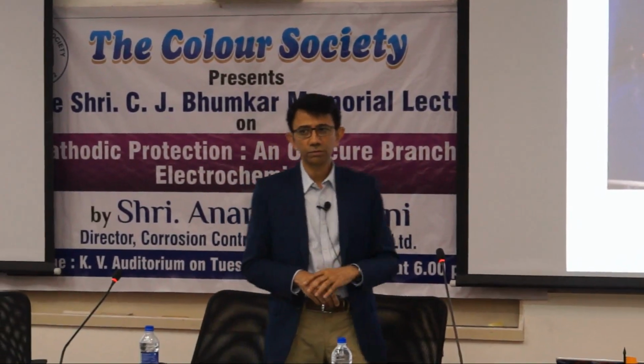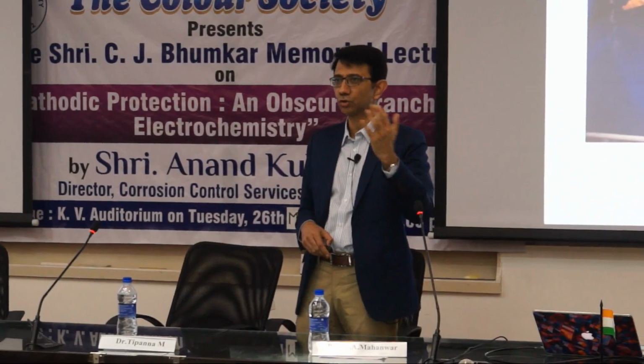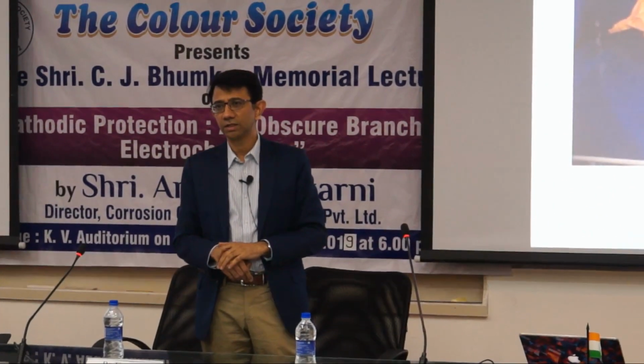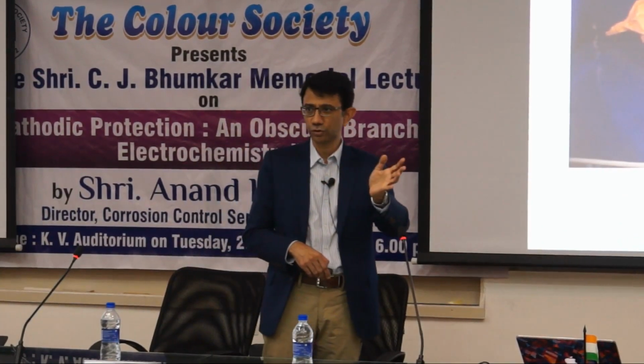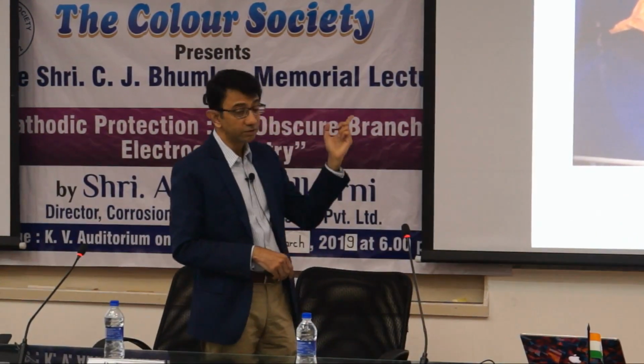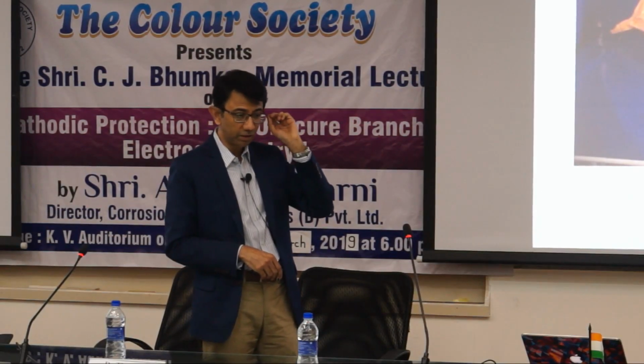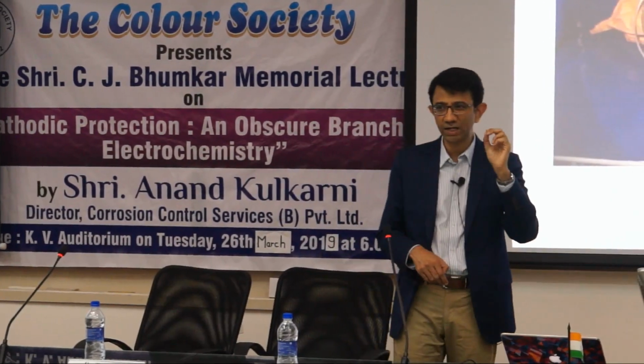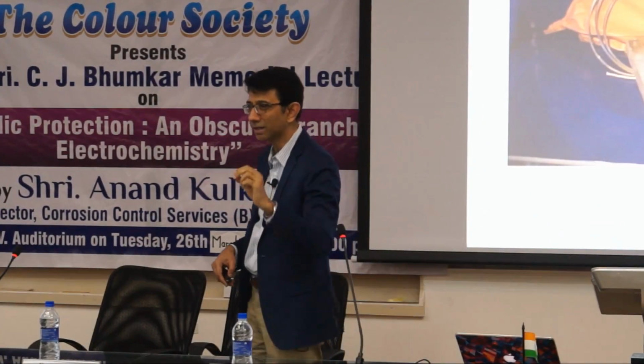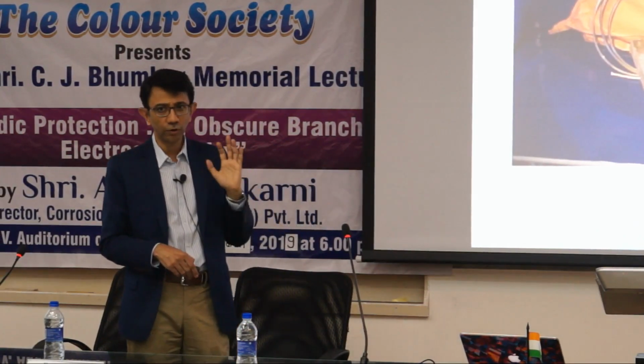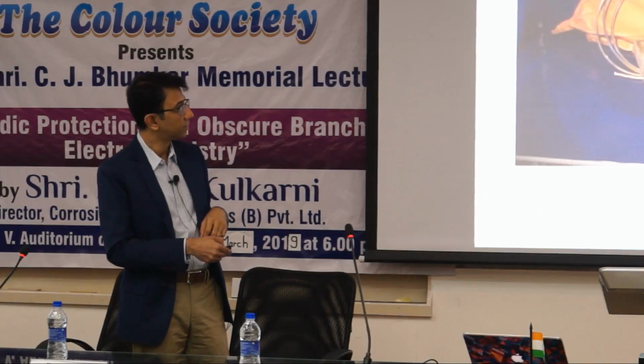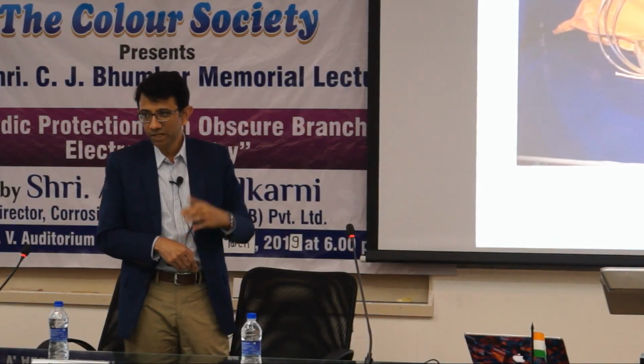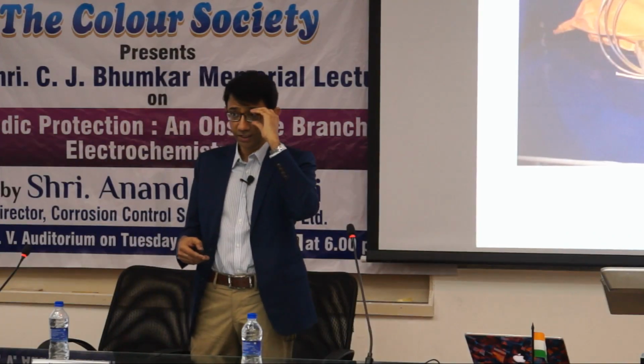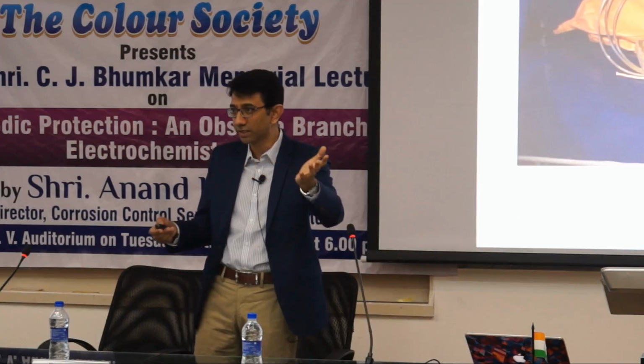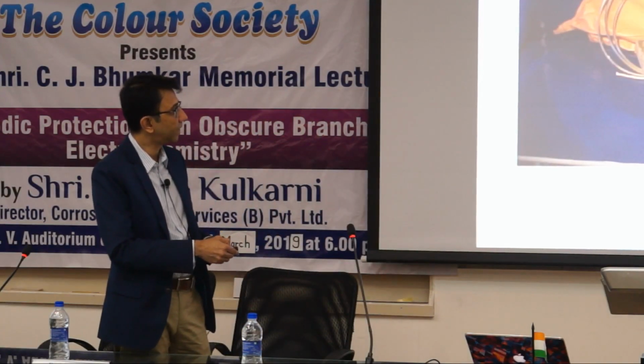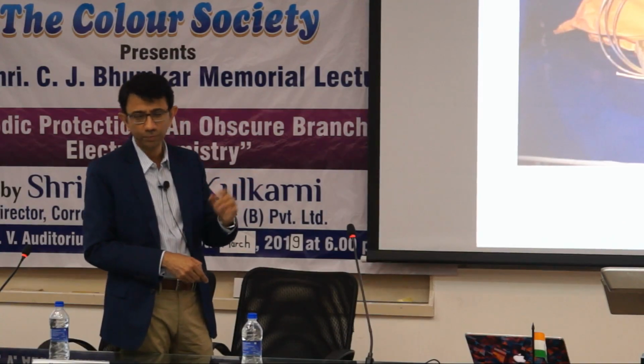Also, if you have carbonates or bicarbonates or nitrates, then we find that the efficiency of zinc goes down. Its potential shifts to the noble side. It doesn't really act as an anode. The other interesting thing about zinc is zinc needs to be extremely pure. So, we're talking about a 99.99% pure zinc for it to act effectively as an anode. Because for it to act effectively, it has to have a sufficiently electronegative potential. It has to be sufficiently active.